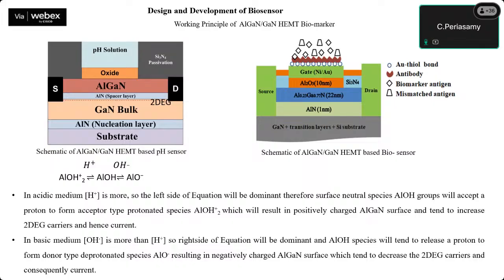Similarly, one can deposit a different functional material or layer for different diseases. Whatever diseases you wish to detect or study, we have to select an appropriate functionalization layer. Choosing that functionalization layer is important. For example, this Al2O3 layer one can use to detect a particular heavy metal ion, but Al2O3 will detect not only, for example, mercury, but it will also detect lead ions. So you have to choose appropriate functionalization materials. That is more important.